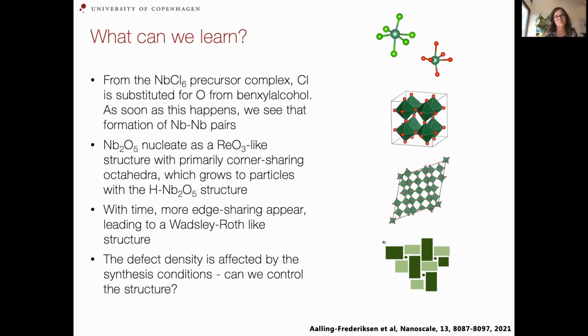So we see that we have them connected. And then we nucleate this niobium oxide structure, and then we form the next level, starting these edge sharing octahedra, and then we get a defect structure in the end. And now what we can see is that the defect density is affected by the synthesis conditions.